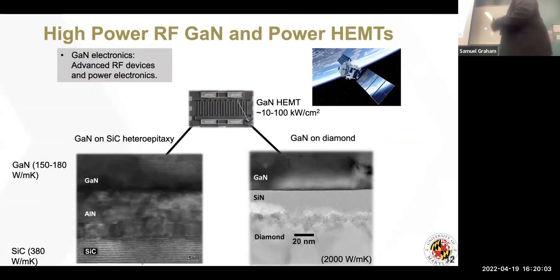Okay, so let's start out with gallium nitride. Remember, I'm going to have a higher thermal conductivity, and as I start increasing band gap, it's going to become more challenging. One of the interesting things is that when I showed you the cartoon of gallium nitride and silicon carbide, the crystal structures are not the same. So what I have to do is put a material in between, like aluminum nitride. This allows me to sort of grade between this crystal structure, lattice constant, this lattice constant. And so this layer right here can cause thermal resistance.